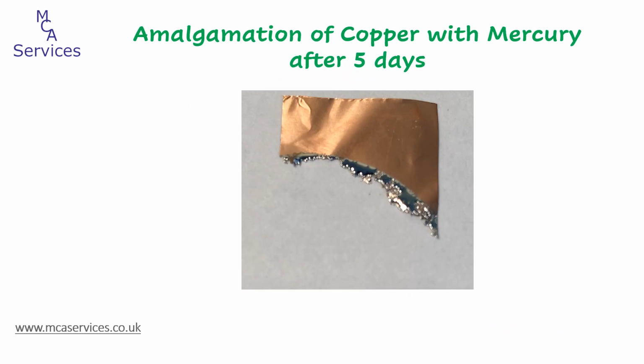After 5 days, we removed the copper from the mercury, and we can see that the section of copper that had been in contact with mercury completely disappeared, so it's dissolved in the mercury. We can also see that the mercury is changed around the edge. Normally mercury forms a droplet on a smooth surface because its contact angle is actually really high, about 130 to 140 degrees. But during the process of amalgamation, the contact angle of mercury changes, it falls below 90 degrees, and we can see around the edge it becomes wetting. It now looks more like molten solder.